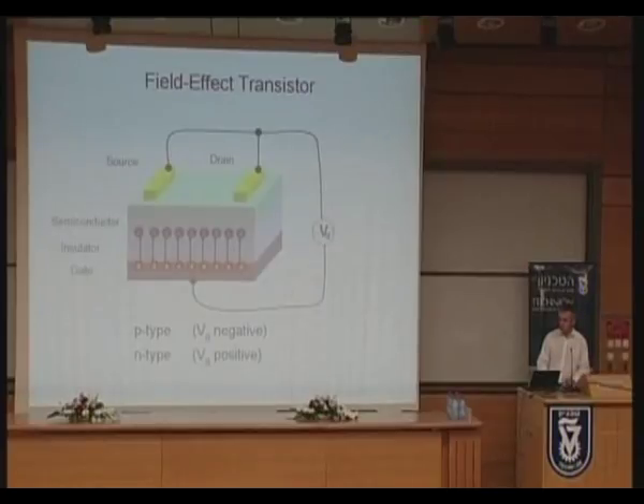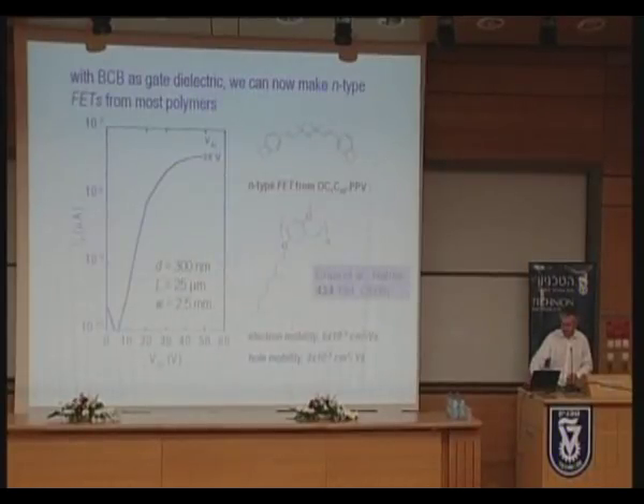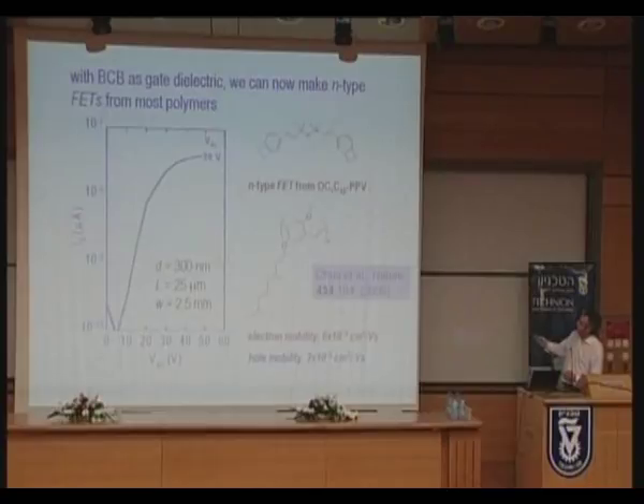The reason is actually because a lot of people have used silicon dioxide as the dielectric, and the hydroxyl groups on the silicon dioxide turn out to be susceptible to electrochemical reduction to form SiO minus states, rather than allowing injection of electrons into the semiconductor conduction band. And if you go to the right dielectric, and those turn out to be organic dielectrics, in this case an example of a thermally cross-linkable polymer, BCB, benzocyclobutene, then it turns out that we can get N-type behavior just as easily as P-type behavior.